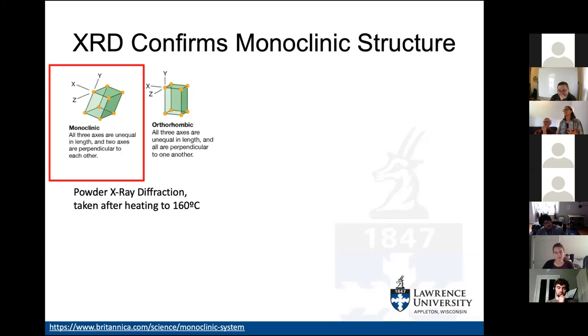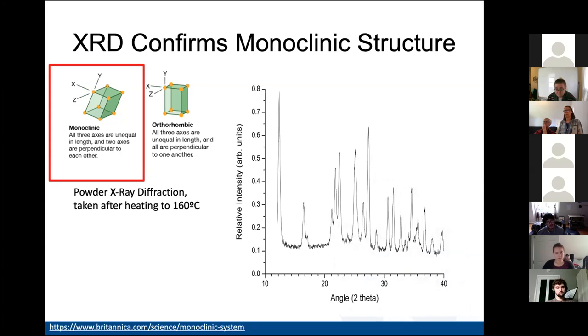The phase transition temperature for deuterated Diisopropylammonium seems to be around 160 degrees Celsius, so we heated the crystals to 160 degrees Celsius. A heated sample of deuterated Diisopropylammonium gives a shifted monoclinic structure, and the peaks around 16 degrees and the evenly spaced triplet around 22 degrees are telltale signs that the heated deuterated Diisopropylammonium crystal is in the monoclinic structure, since these features are the same on X-ray diffraction graphs of ferroelectric non-deuterated Diisopropylammonium crystals.